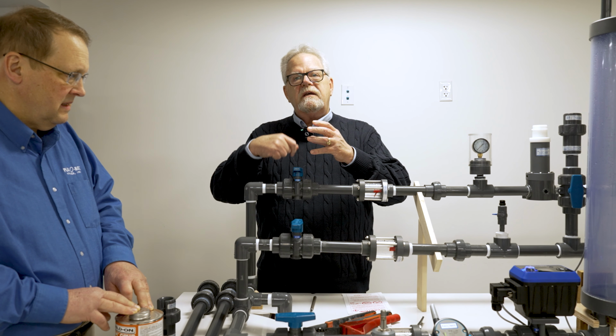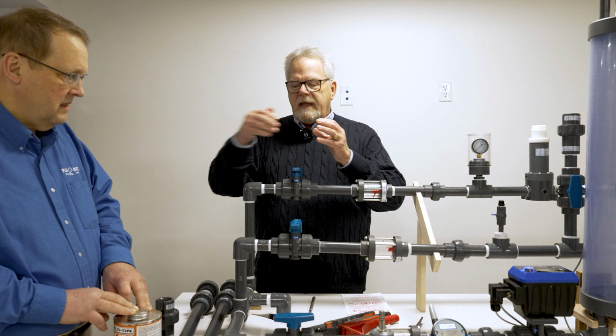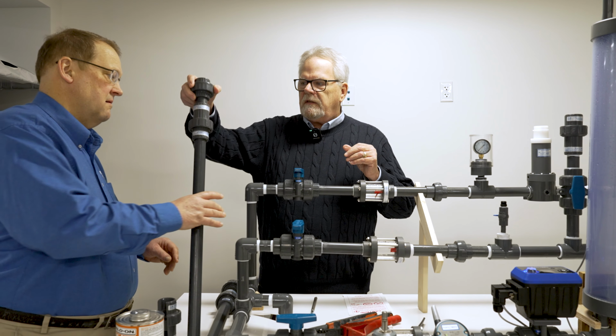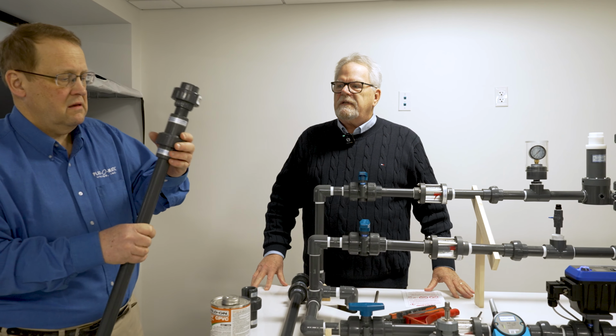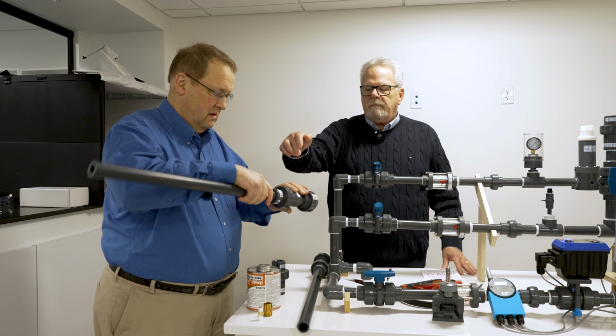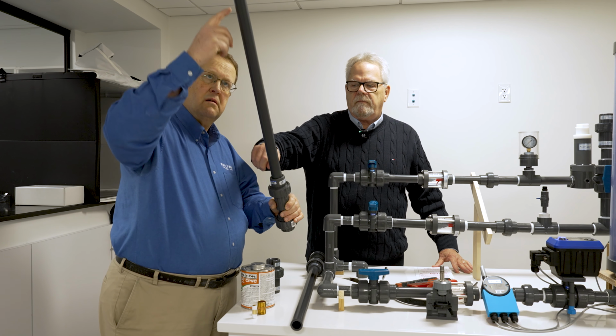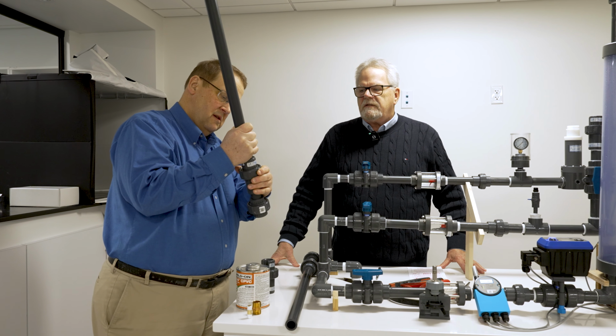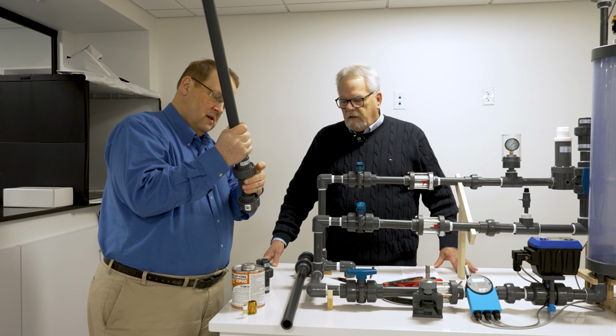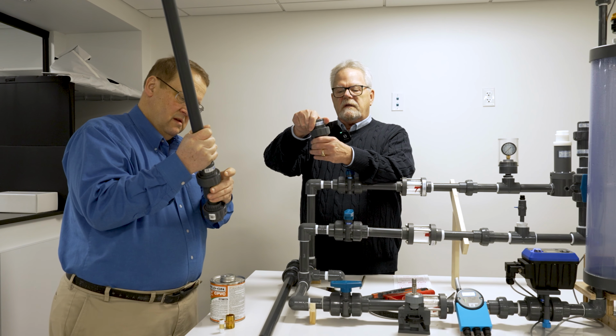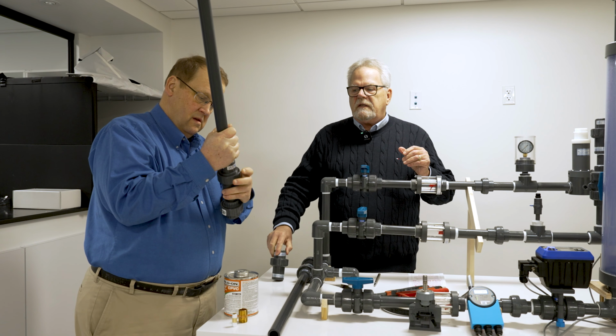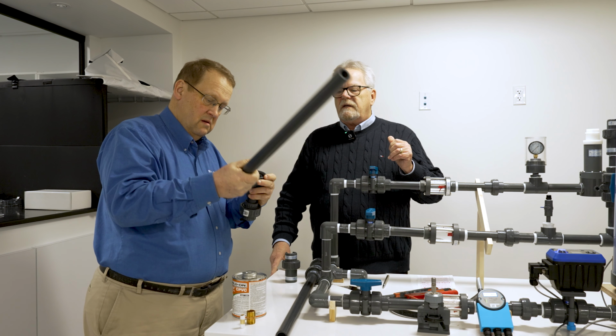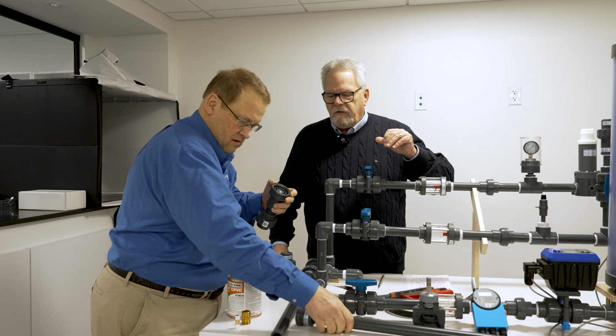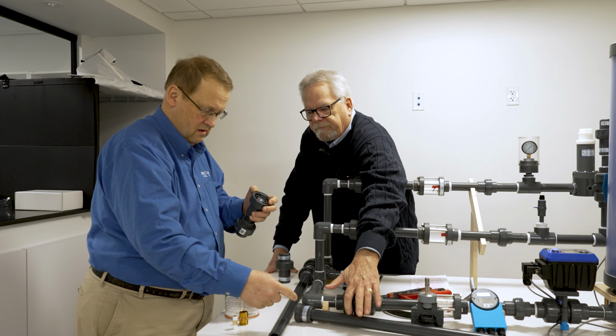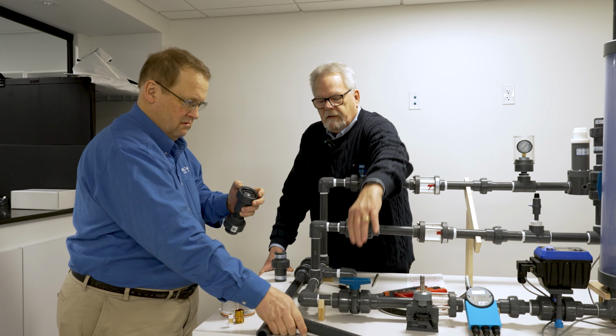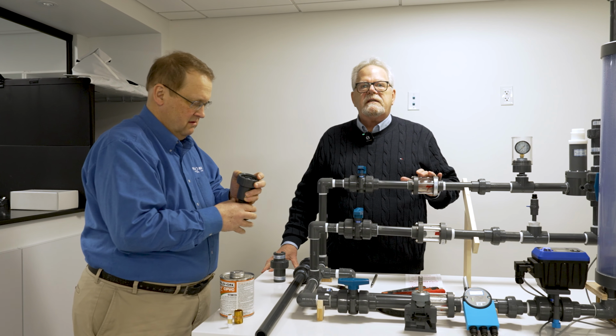If you put too much into your joint, it can slide down, as we'll show here on these samples, where customers had solvent cemented the Plast-O-Matic ARV to a standpipe. And they solvent cemented the entire assembly as is, as received from the factory. They did not remove the individual pieces first. And what happened is the glue ran down through the joint from the top down and found its way onto the seat.